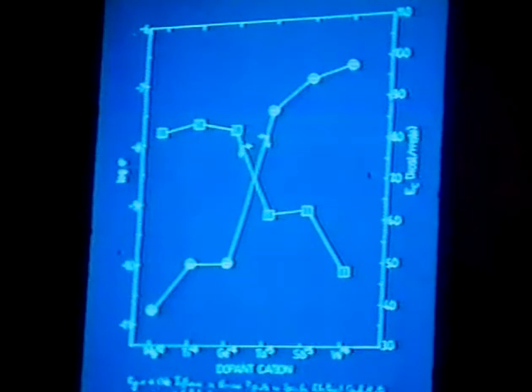is increased by up to 3 orders of magnitude when the parent material is doped with cations of higher valence. Similarly, the activation energy of electron conduction is reduced when the material is doped with cations of higher valence. These results indicate that under the conditions employed in this study, doping did indeed occur. The effects of carrier doping on the chemisorptive parameters of the supported metal crystallites were investigated by static adsorption of oxygen, hydrogen, and carbon monoxide.